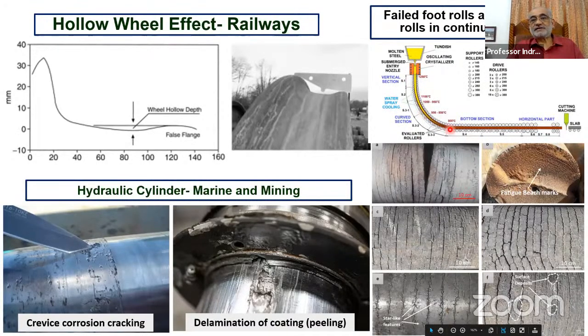Look at the continuous caster. From the tundish to the nozzles through which actually the hot metal goes vertically into the rolls. And now you have series of rolls, and these series of rolls not only are responsible for thickness reduction, but also heat extraction and turning a skin depth solid layer into a completely solid sheet by the time it comes out of this train. Now, these rolls actually encounter very major damage because of high temperature, high corrosive environment because of the fluxes used, and also the mechanical forces. So together they create a very, very challenging situation.